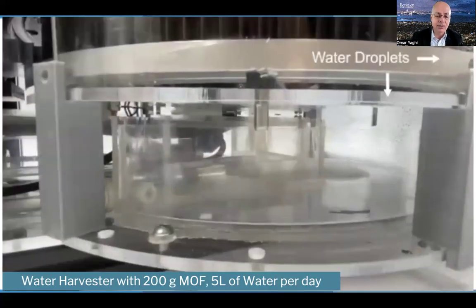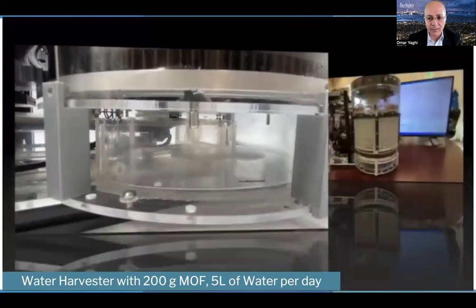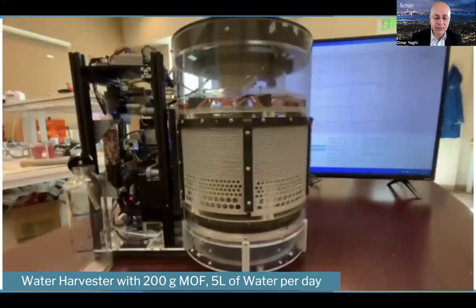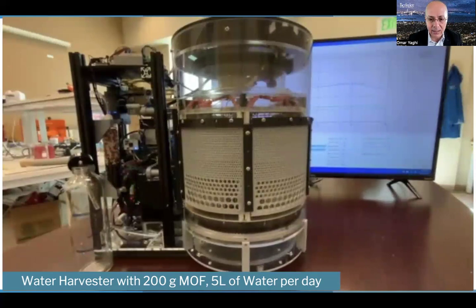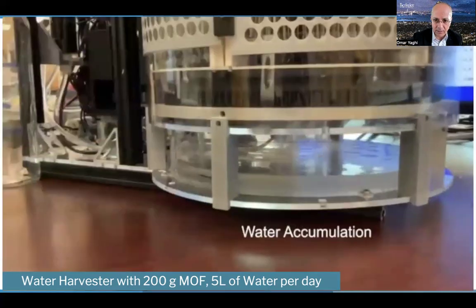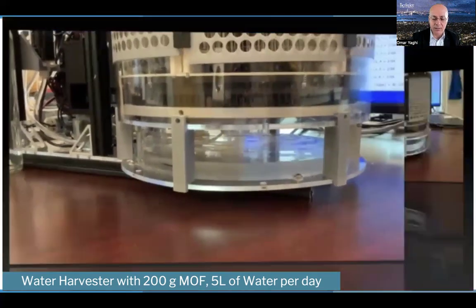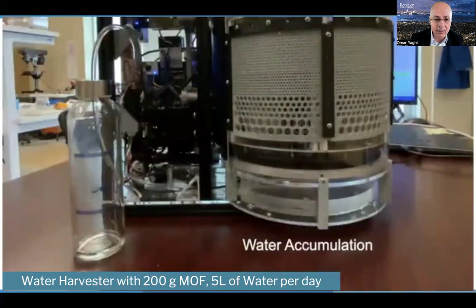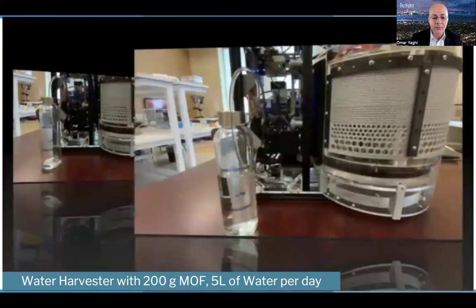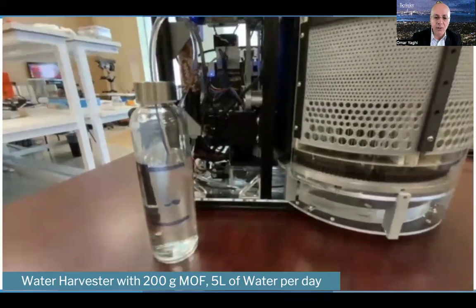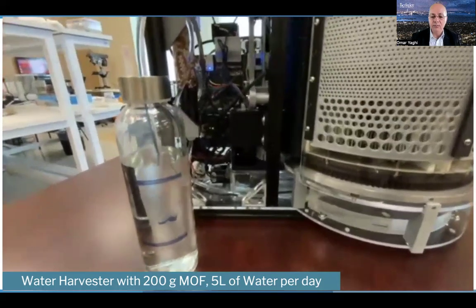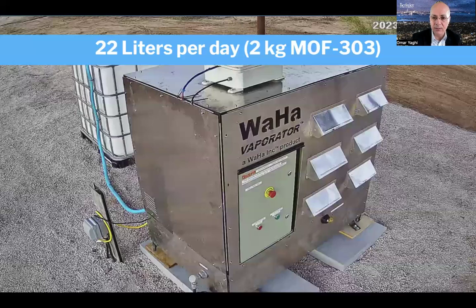The air touches the MOF, which extracts the water from the air and collects it, and then when it's full, it gets heated, and the water condenses, as you see here, accumulating at the bottom of the device. You deliver 5 liters of water every day from 200 grams of MOF. If you want more water per day, you can use more MOF. And this is something that we are doing here. Here's a device that uses 2 kilograms of MOF and can give us 22 liters of water per day.